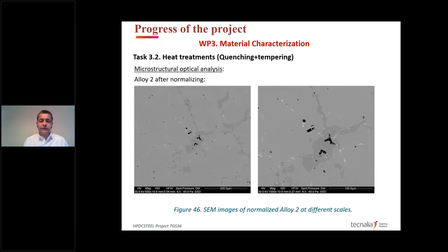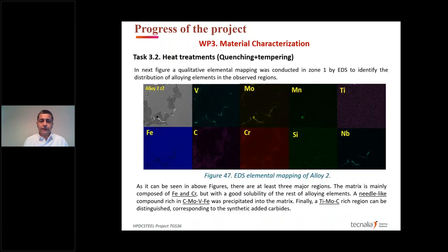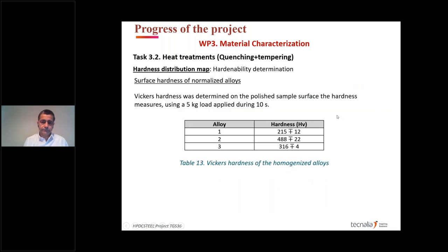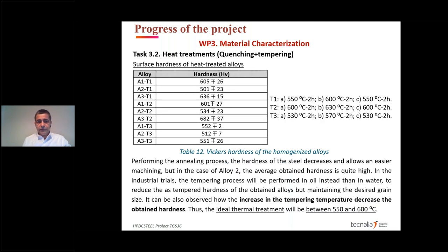Here we have some images with the distribution in the steel. We have the vanadium, the molybdenum, and the titanium. The hardness of the three steels was also tested. We see here that alloy two has a very high hardness after normalizing. After the thermal treatment, we also have quite high hardness, but we should check for an ideal thermal treatment.